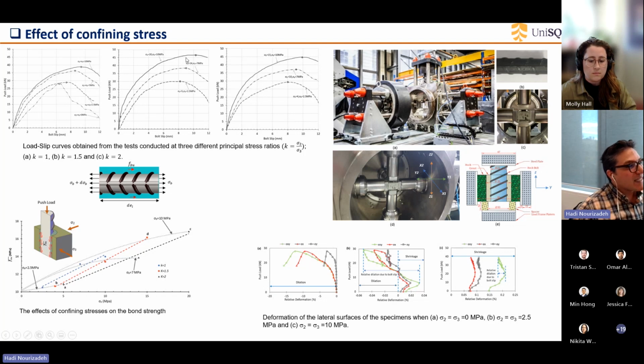This is almost equal to when we have sigma 2 equals 15 MPa and sigma 3 equals 10 MPa. These are very important when we design supporting and reinforcing systems and for the stability of underground openings. We also considered and analyzed the bond strength in these scenarios. The bond stress is due to the interlocking and the cohesion between the bolt and the encapsulation agent. Here you can see the results in this specific diagram.